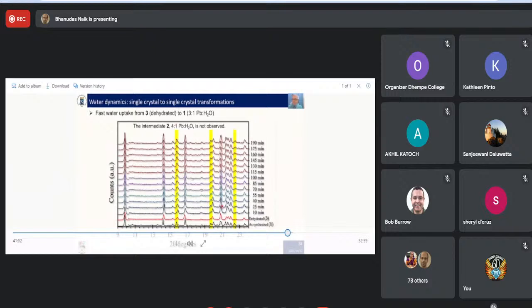So if we have 1, which is synthesized as this, peaks here, you can see I've highlighted a few key peaks in 1. If you dehydrate 1, you can see that it remains a crystalline structure. This is a single crystal to single crystal transformation. So you can see even in the powder that it's a nice crystalline structure still. But you've lost basically this peak here. This peak here has diminished, and this one is lost completely.